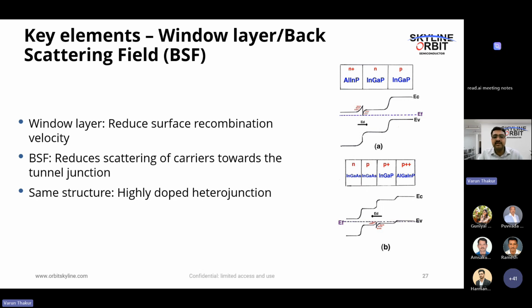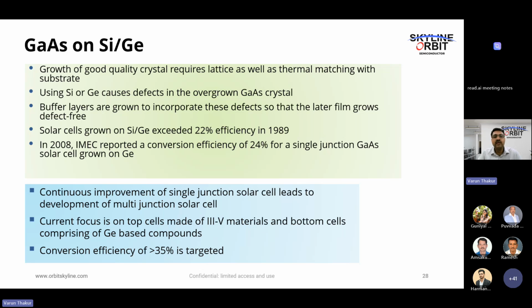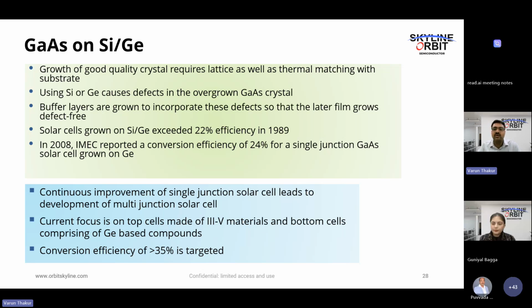So I hope you can understand that all these elements are basically used to increase the efficiency of the solar cell. So now I'll just move on to some different kinds of solar cells that have been grown in the recent past, using silicon or germanium as the substrate. So gallium arsenide growth requires a good quality crystal. So usually we grow on gallium arsenide itself or on some lattice-matched or cheaper substrate. So we need the overlayer to be the least defective, but also to be cheap, right? So how do we match both things? So what people have done to reduce the cost is to grow buffer layers. Okay, they have used buffer layers. These buffer layers incorporate the defects, so the film grows later defect free, right?